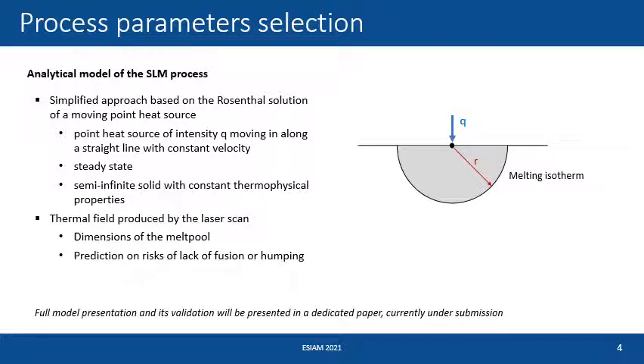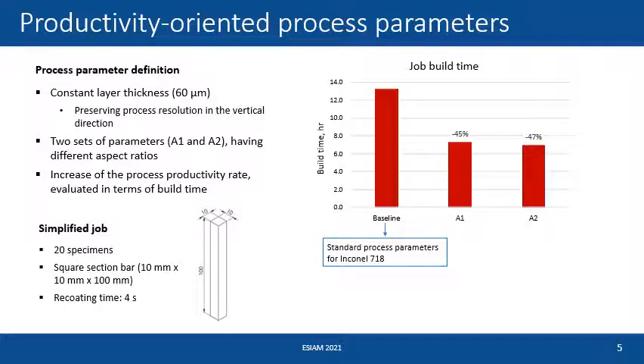This approach allows us to obtain the thermal field produced by a single laser scan in terms of the dimension of the melt pool and prediction of the risk of lack of fusion or humping. The full model will be presented with its development and validation in a dedicated paper that currently is under submission. The process parameters were devised keeping fixed the layer thickness, in this case 60 microns, and so preserving the process resolution in the vertical direction.